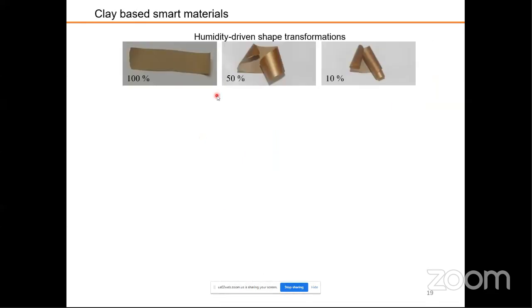Now, because this material combines two different natures of material, it's very sensitive to external stimuli. For example, when you change the humidity around it, it changes its shape. If you put it in a very humid environment, it becomes flat, like a strip. But when the humidity decreases to 50%, it curls down and rolls up like that. And when it goes to 10% humidity, it's completely curled up into a roll like this.